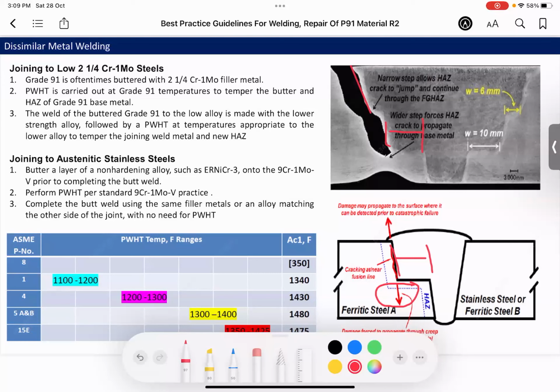This is recently mentioned in API 582 about having step bevel in dissimilar welds. API 582 Appendix F in the 2023 edition. They have published a good practice for P91 material. And this is one of the requirements that should be followed when having a dissimilar weld for joining P91 to low alloy steel, for example, P22 material. So the steps are as follows. We should butter the weld with P22 filler material, and then do the PWHT as per grade 91 requirement,